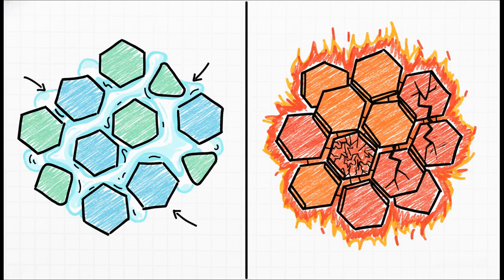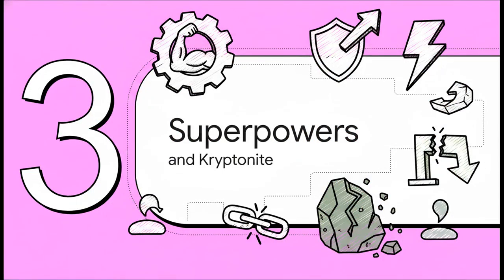So to close those microscopic pores, we have to rely entirely on extreme heat and solid-state diffusion. It requires multi-step firing, and we have to be incredibly careful with impurities. Things like silica or iron can form weak secondary phases that compromise the entire structure, and we absolutely need maximum strength here. Which brings us to Section 3, Superpowers and Kryptonite.